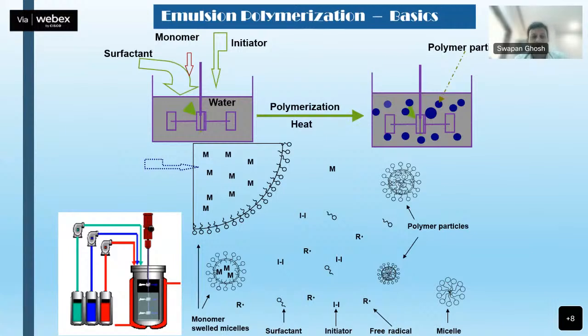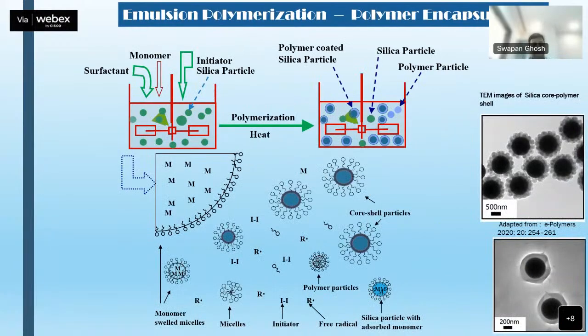Now let me come back to the encapsulation point. What will happen here? Earlier you could see water, initiator, monomer and surfactant. Now what we are doing is adding silica particles in the beginning itself in the reactor. And we'll conduct the same polymerization, we'll heat, we'll add all the ingredients, whatever it is. And at the end, we'll have silica particles which are coated by polymers based on whichever monomer we decide.